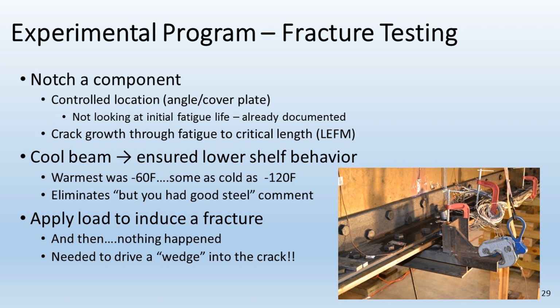Now, the reason for the minus 60 is because that is the lowest anticipated service temperature in the northern states of the U.S. So to be conservative, we tested everything as if it was in the worst location. The reason for the minus 120 is because our newer steels, fortunately, but unfortunately for me as a researcher, are quite tough. And what we didn't want is that if we did all our tests at room temperature or with high toughness, the research would only be applicable to girders or steels that are tough, that are modern, not necessarily cold or, more importantly, old.